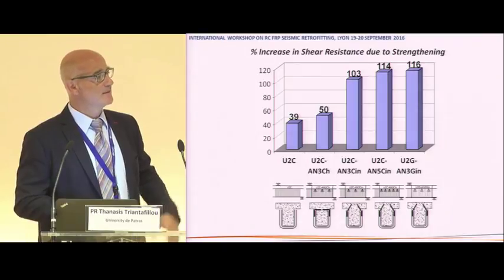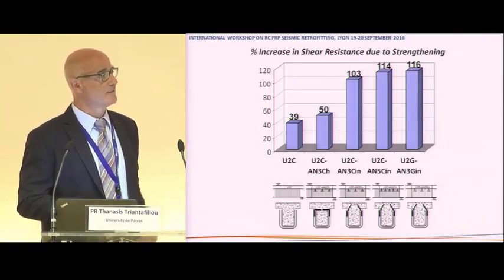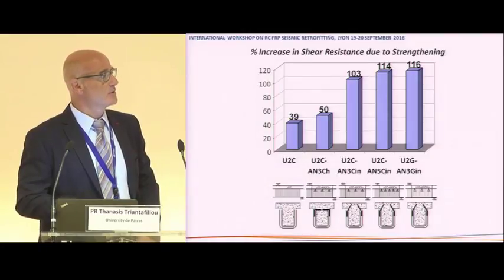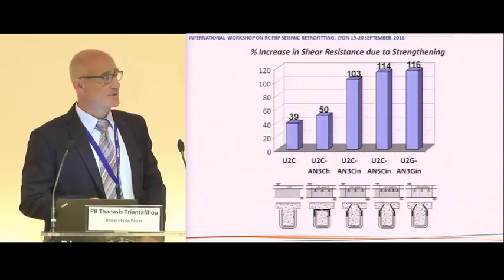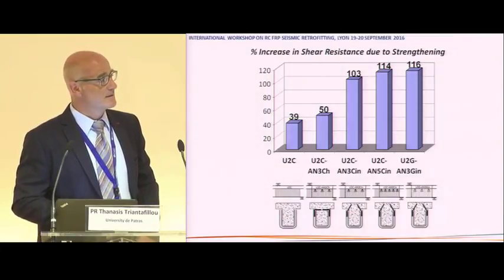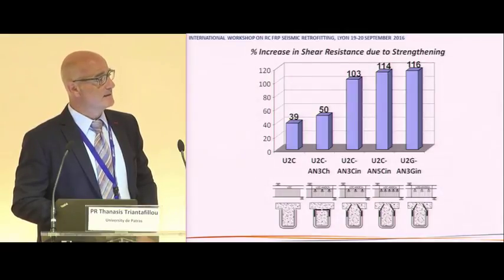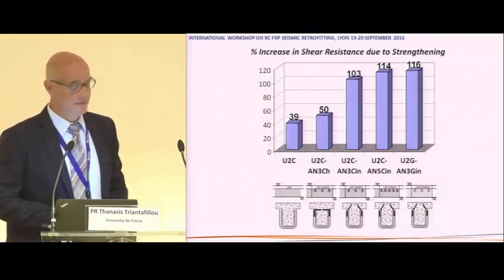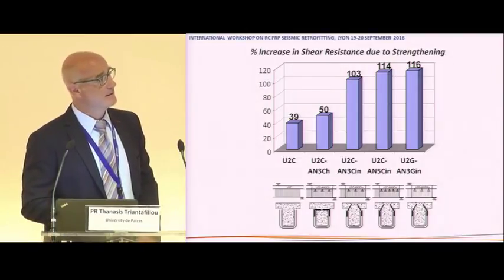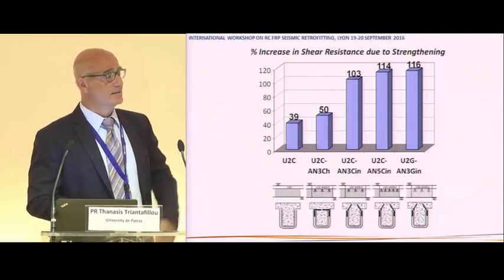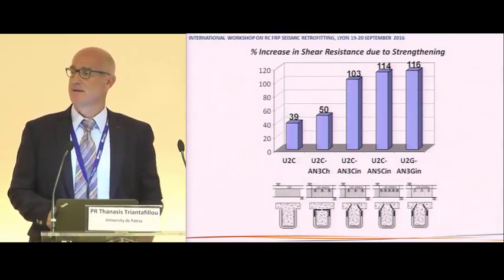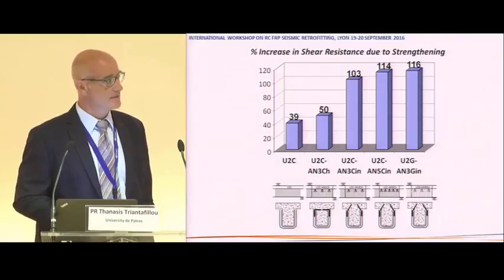You may see the extra shear capacity provided by an open jacket to a typical T-beam, we have something in the order of, let's say, 39–40% if we do nothing about anchors. And then depending on the configuration of the anchors, we can increase that capacity from 39 to 50 to more than 100%. Apparently the best system is somewhere here where those anchors are placed nearly vertical and not horizontally in the web, but as vertical as practically possible through the slab. So if I compare that column here to the very first one, I have a tremendous increase in the effectiveness of the system if I combine those U-shaped jackets with anchors.